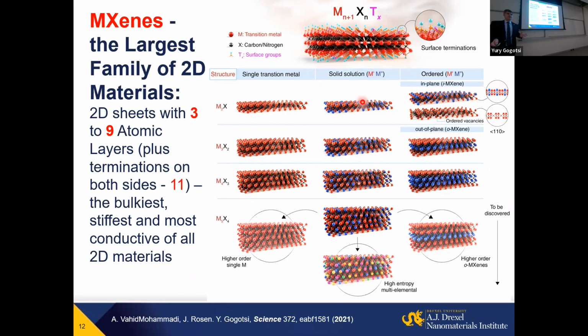And let's just do math. You have 12 transition elements, carbon, nitrogen, and 4 different structures. You already end up with at least 100 stoichiometric compositions here, not counting 26 that have been predicted theoretically as out-of-plane ordered, and another probably 20, 30 in-plane ordered structures. Now multiply by 10 surface terminations already available, and you end up with at least 1,000 stoichiometric compositions within the MXene structure. But we have all the solid solutions, and even high entropy multi-element MXenes were reported last year. So you basically have virtually an infinite number of possibilities. We just need to learn how to design them, how to synthesize them, and how to use them. And we can build a new world with this material.